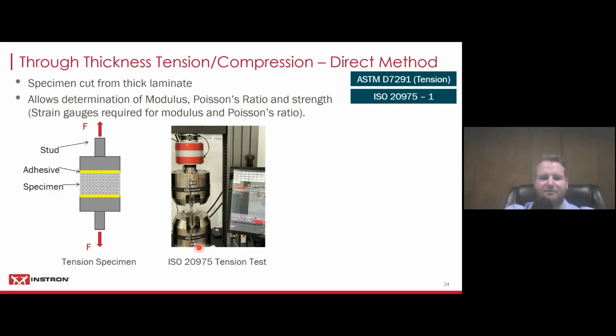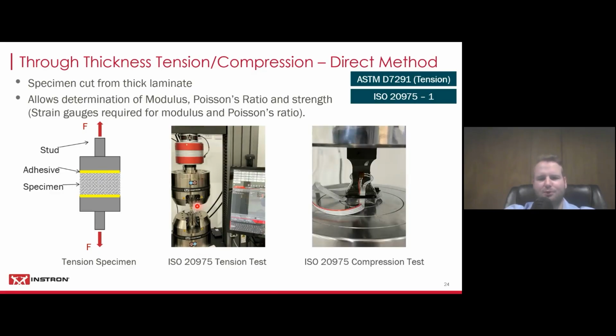This is the ISO 20975 in tension on a testing machine, and this is how it would look in compression with the 2 platens coming down. You can see here the strain gauges being connected to the specimen to determine the modulus and the Poisson's ratio.